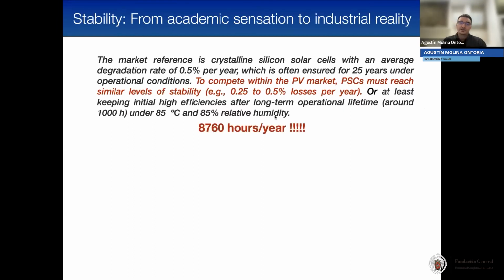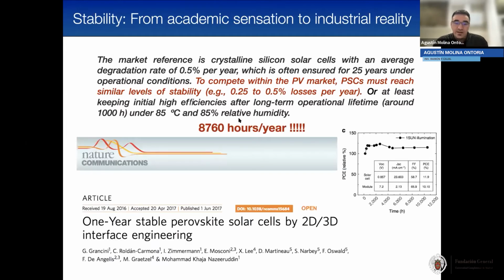The year has more than 8,000 hours. So back in 2017, the group of Professor Nazeeruddin reported a perovskite that was stable for more than 1 year, with efficiencies not higher than 12%, but this is unprecedented. I mean, this is extremely good because it's stable for 1 year. And for doing that, they used a 2D/3D approach.